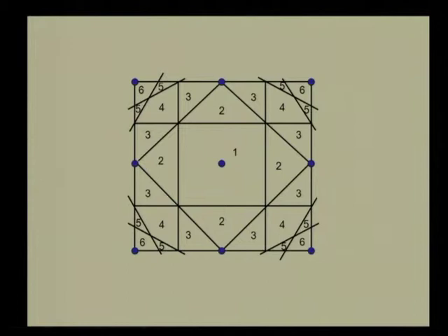So, originally we would have some material that would have a lattice in real space. Using the standard conventions for how you would get the corresponding reciprocal lattice, we would generate the corresponding reciprocal lattice. In that reciprocal lattice we would identify the Bragg planes similar to what we have just done. Once we have identified the Bragg planes, using the definition of what is the nth Brillouin zone, we will identify the nth Brillouin zone. So, the nth Brillouin zone requires you to cross n minus 1 Bragg planes, but prevents you from crossing the nth Bragg plane. So, between the n minus 1th and the nth Bragg plane you have the nth Brillouin zone. Okay. So, this is something that we have seen in 2 dimensions.